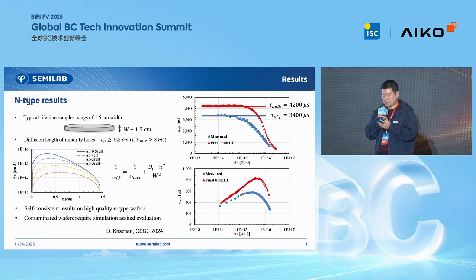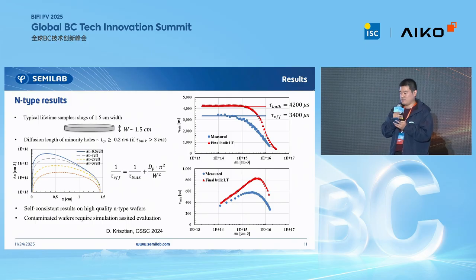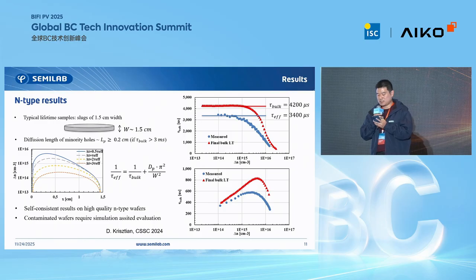The good thing is that this contribution of surface recombination can be corrected precisely. So bulk lifetime can be determined accurately. At the same time, our simulation also provided the same result at low injection levels. This indicates the reliability of our model.